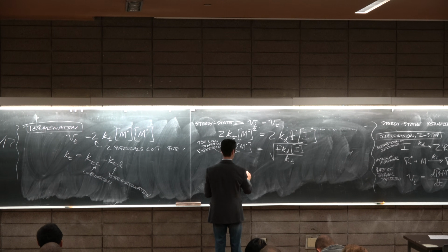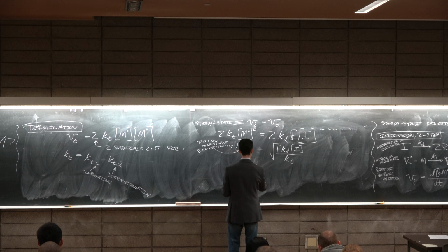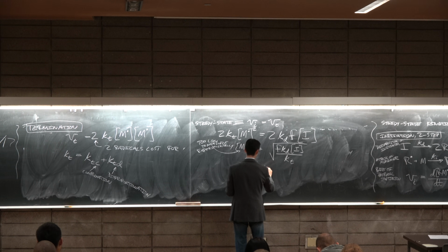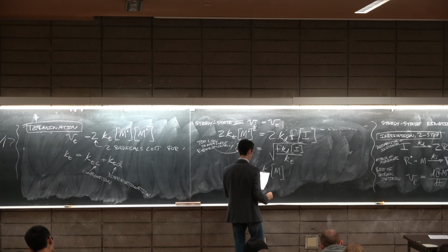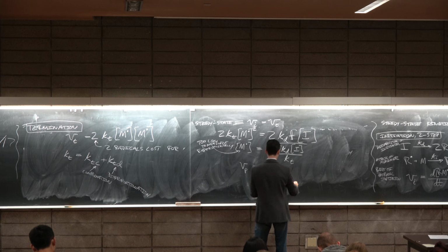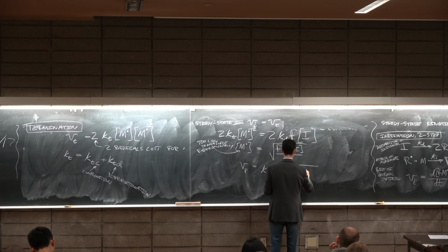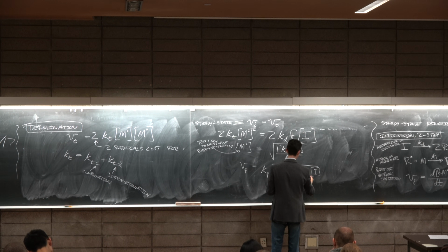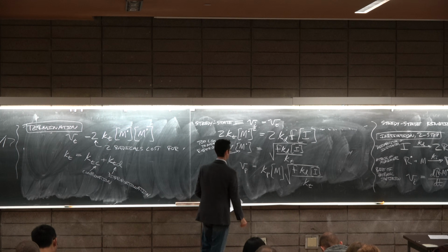We have by substitution Vp, the rate of propagation, is Kp times the concentration of monomers in the system times the square root of F Kd, concentration of the initiator, over the rate constant of termination.